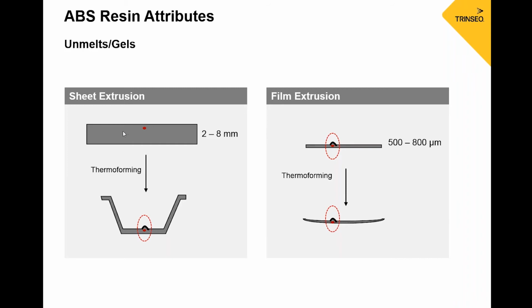So in sheet extrusion, where you might be extruding a thick sheet, the gels can be throughout the cross section of that sheet, and even though you may not see them in the sheet as it comes out of the extruder, it may become more visible or more detrimental to causing defects when it's drawn down in the thermoforming process. But a lot of times you can see the defects in the sheet extrusion as well, but it becomes more prevalent the thinner that material becomes, the thinner the substrate becomes.